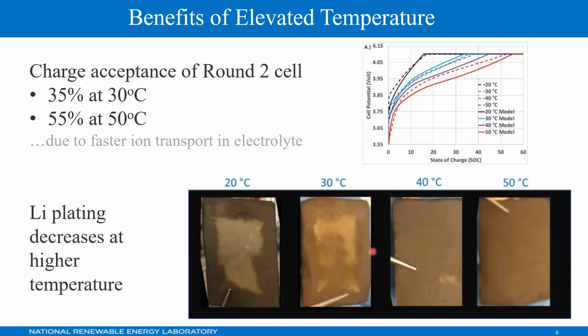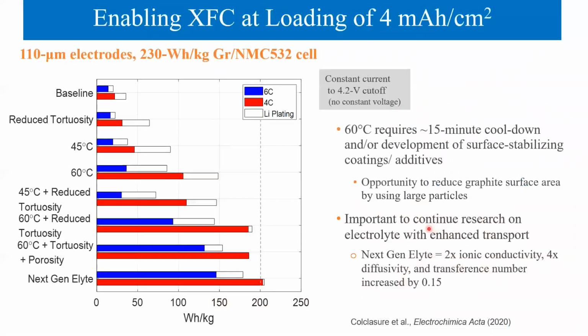The bottom figure illustrates pictures taken of the graphite anode in discharge state after cycling at different temperatures. A large amount of lithium, shining silver areas, are seen for the cells opened at 20 and 30 degrees Celsius. Conversely, very little lithium plating is detected for cells opened at 40 and 50 degrees Celsius.